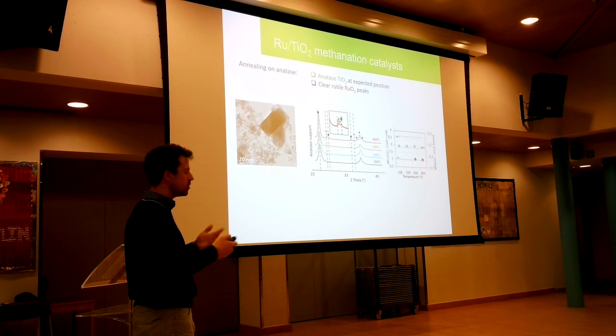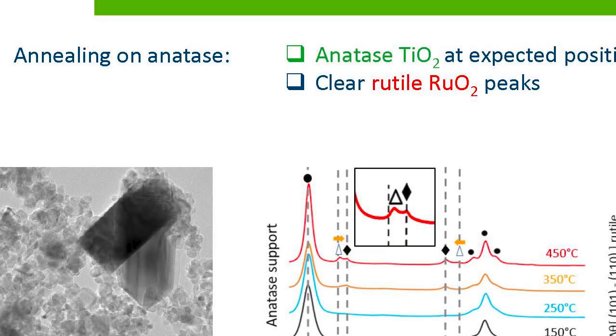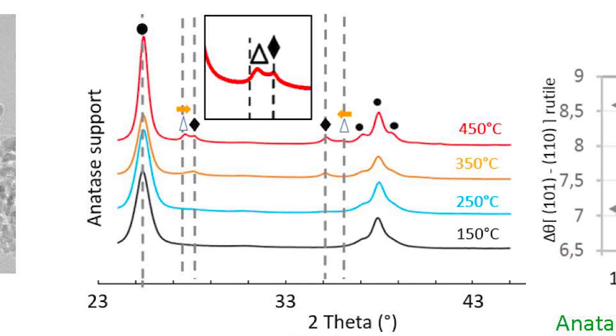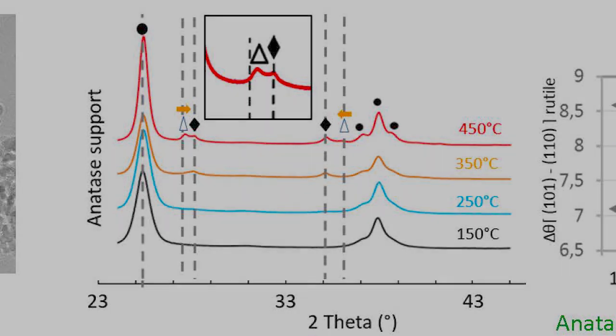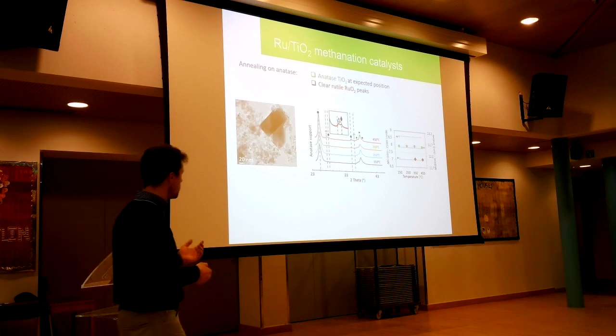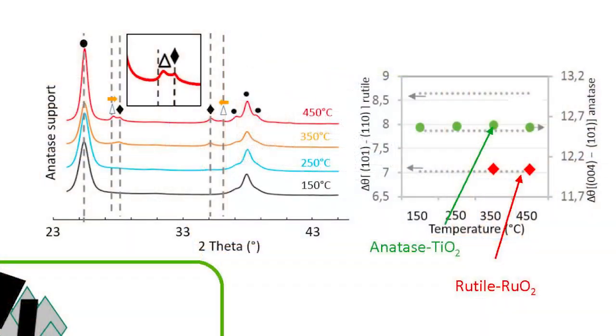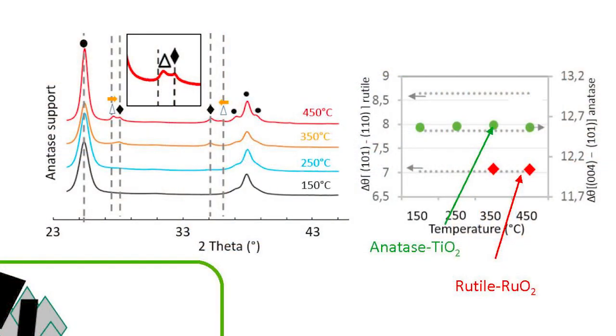So if you look at the XRD, so X-ray diffraction, the catalyst that was just prepared and just heated a little bit on anatase in this case, we see the pattern with the circles there, the typical patterns of the anatase titania support. We calculate a kind of parameter here, which is the split between those two most intense peaks there. And we found that anatase landed exactly where it is expected, so no big surprise. This is anatase, no problem.